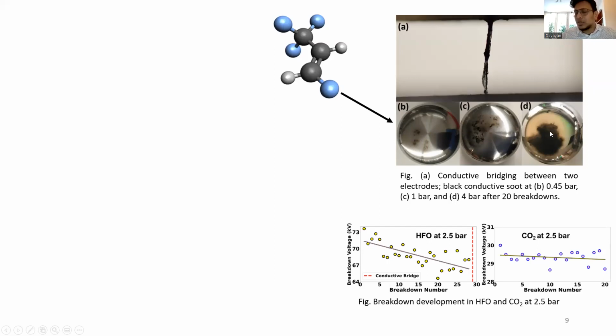And for 4 bar, you almost have a pretty much dark electrode, like it's completely black. And in some cases, you also have the high voltage electrode bridging the grounded electrode. You almost have this conductive channel of pure carbon soot forming between them. And then you can't ramp up the voltage, and it's like a perfect short circuit. And imagine using this in the GIS, it's a mess.